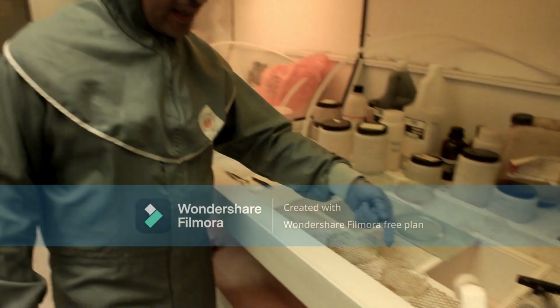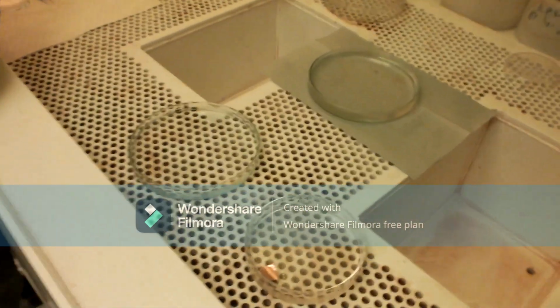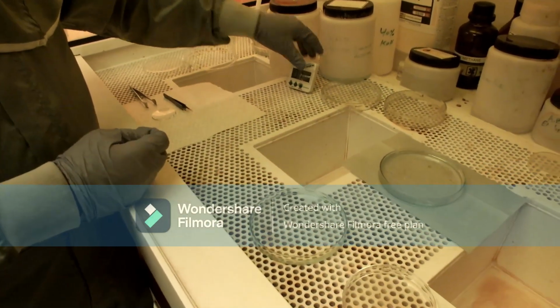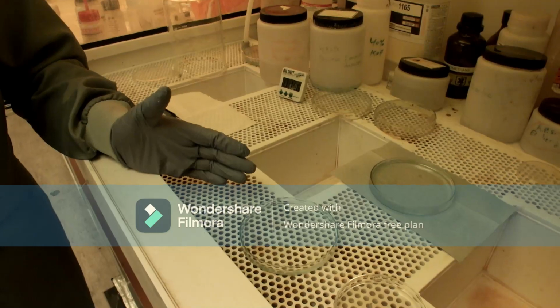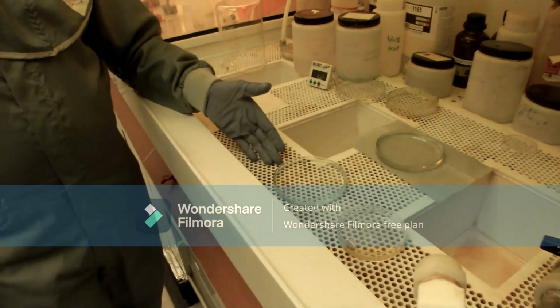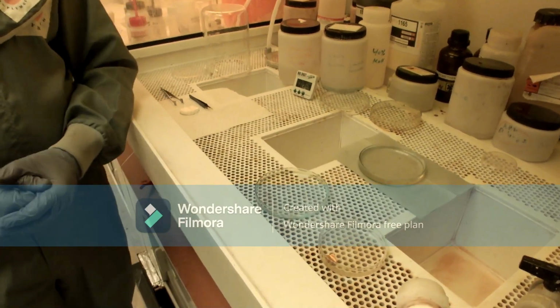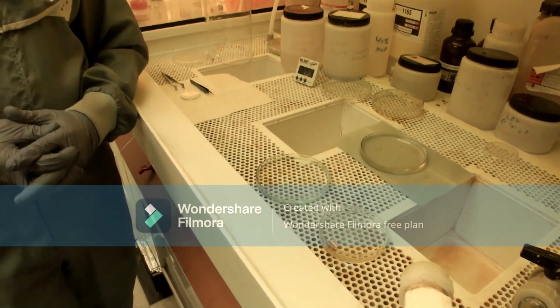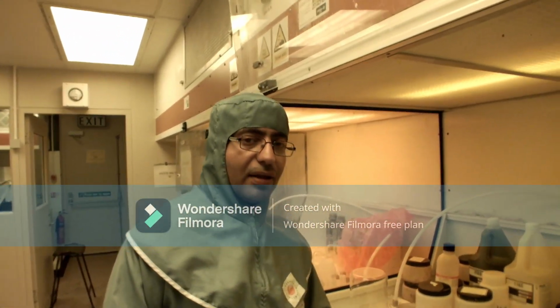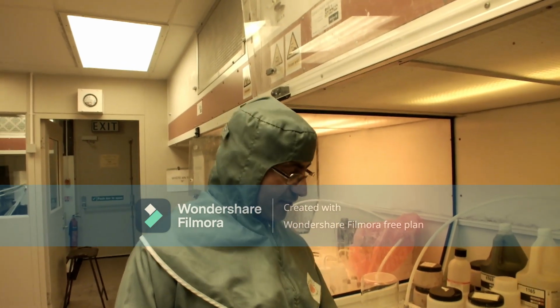Now we will etch the second graphene layer, and I put the sample floated in nitric acid solution. I'll keep it for 2 minutes. Then after this etching, we need to float my sample in DI water to stop the etching process. After this, I'll move to the last step of etching in ammonium persulfate to completely remove the copper foil. Then after that, we will start the wet transfer process. 1 minute and a half left.